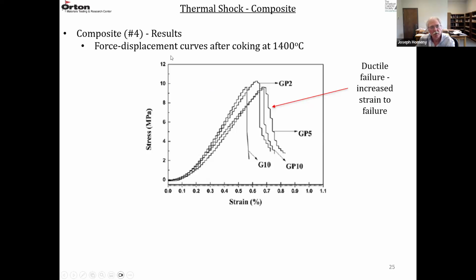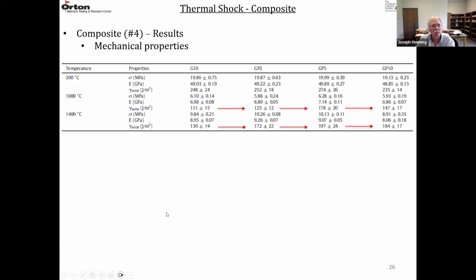And then the load displacement curves for material coked at 1400 degrees C. Again, you can see that they're non-linear, they're not as brittle, and they tend to be more ductile. G10 is still a little bit on the brittle side, but they have an increased strain to failure for the ones with the pellets, getting closer to 0.9%. So the higher the strain to failure, the better the samples can accommodate the thermal shock damage, and the better the thermal shock resistance.